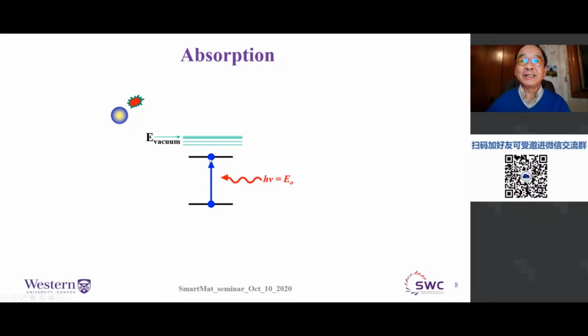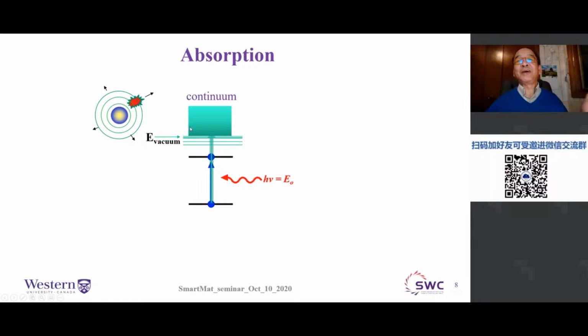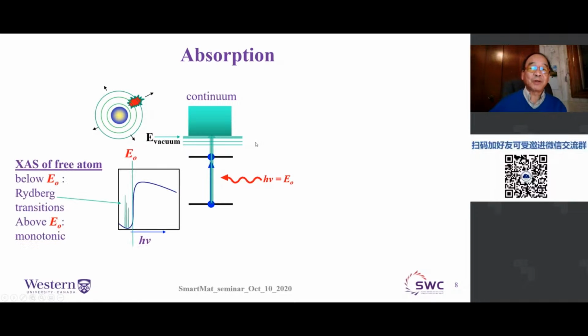If you continue to increase this energy, ultimately at some point you're going to kick the electron all the way into the continuum. At that point, the electron will propagate away as a spherical wave, and disappear into thin air. If you measure this process in the form of absorption, this is what you will see. Before the threshold, you see these so-called Rydberg transitions, which are bound-to-bound transitions approaching the continuum, which is the vacuum level.